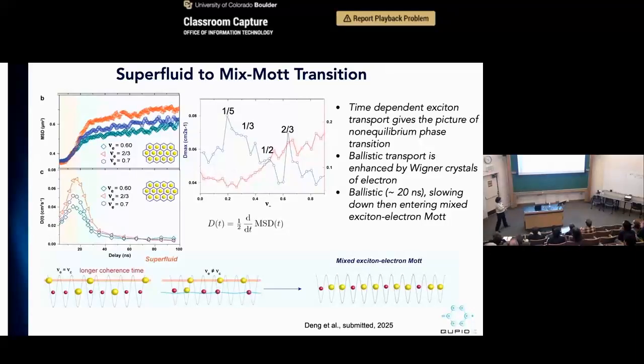So then we can look at extracting the maximum diffusion constant as a function of, this is somehow covered up, but this should be VE, this is charge filling. You can see that in the high exciton density limit you have these abrupt changes, but in the low density exciton limit you just have a continuous change as a function of charge. The reason you have increased transport at low density is because the charge screening increases, so it makes the excitons move around more. Also, if you look at longer time behaviors, in the first 20 nanoseconds you have this drastic ballistic, quadratic behavior, and at some point your excitons also decay away, so that you enter a more diffusive regime.